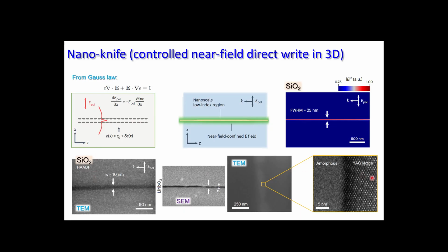On the bottom line, there are different materials but measured by different techniques, but what is common is that we are not using etching. We just make very thin films and see, can we recognize modification? And you can recognize that in silica, it's around 10 nanometers, lithium niobate, so you can write domain inversion if you want, and I think people are trying now to do this. In the YAG crystal, you have crystal and amorphous phases very, very well defined, side by side.